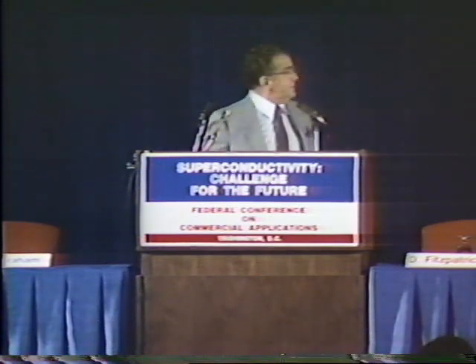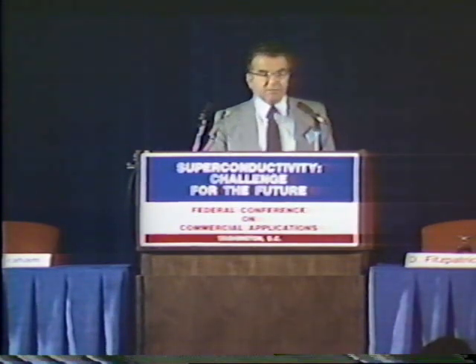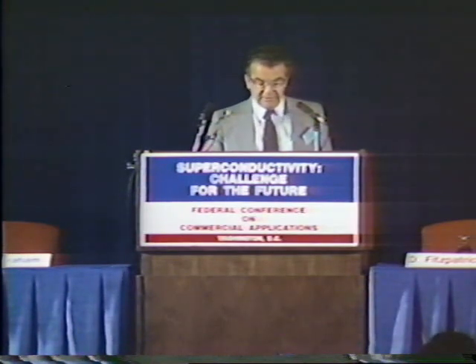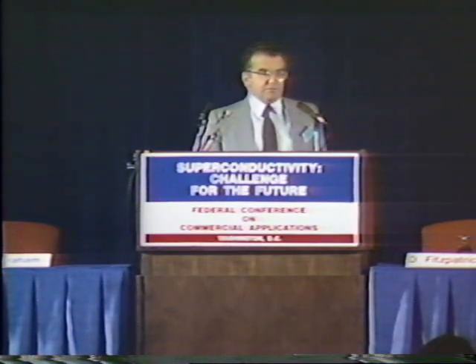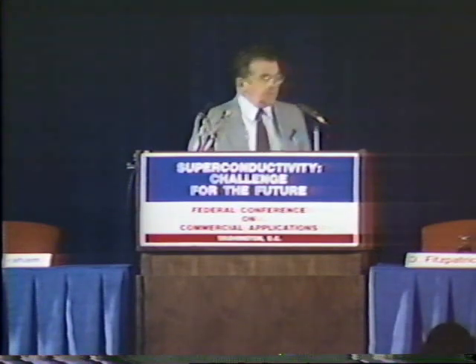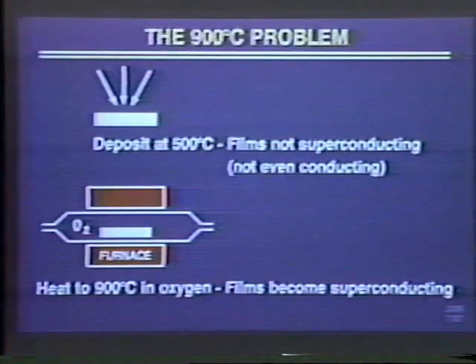So that's two extremes of the methods that can be used, but I don't see that as a constraint. There's obviously lots of choices. But let me come to what I see as the first real problem on the next slide. Let's call this the 900 degree C problem. As I said, those substrates were held at 500 degrees centigrade, which is already a relatively high temperature in processing, typical processing steps using semiconductors, for example. But after those films are made on that substrate at 500 degrees, they are not superconducting. In fact, generally, they're not even conducting.